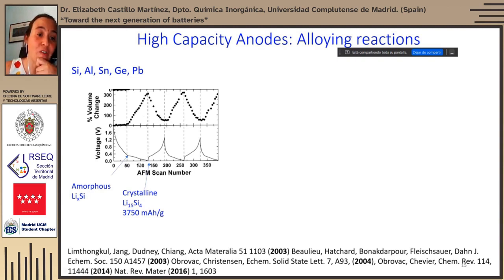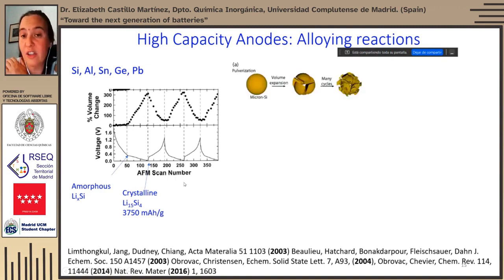For example, in the case of silicon, it can form Li15Si4, which has a capacity which is 10 times that of graphite. However, as you can imagine, if almost 4 lithium atoms per silicon atom enter into the structure, there is a large volume expansion with cracking of the particles, and after many cycles, these particles get completely pulverized.